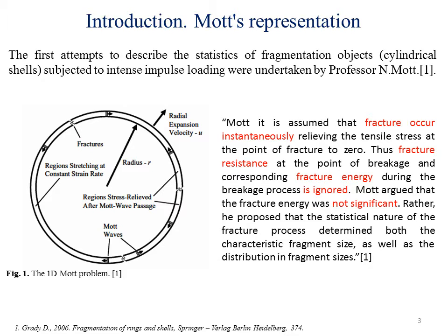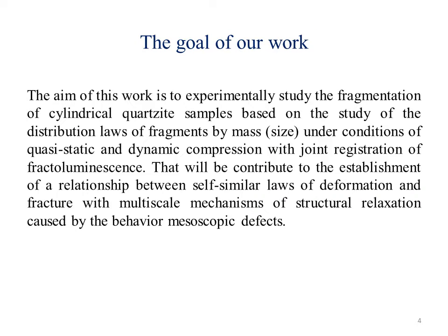Mott believed that destruction was instant. He didn't consider the resistance to the fracture in the rupture point and the corresponding destruction energy in the rupture process. Mott argued that the destruction energy was negligible. He assumed that the statistical nature of the destruction process is determined by the characteristic fragment size and the fragment size distribution.